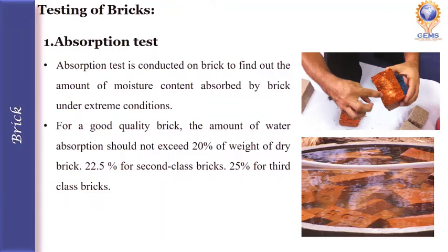This test is used to determine the amount of moisture absorbed by a brick under extreme conditions. We have to take the brick samples from the same stack and weigh the dry weight. After weighing the dry weight, we immerse the brick in water for 24 hours. After 24 hours, we take out the brick and weigh it. The difference between the dry weight and the wet weight gives the amount of water absorbed by the bricks.